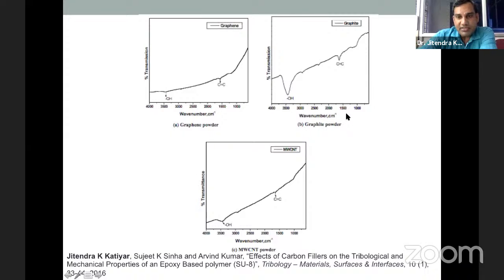And according to this wavelength, whatever frequencies we tested and percentage transmission, we observed in graphite that this hydroxyl peak is very wide and big, in the case of graphite, and in graphene it is very small, and in MWCNT it is still present. So because of the presence of this hydroxyl group, graphite always shows a very low friction coefficient rather than other carbon materials. The other carbon materials are also good, but that depends on the application.